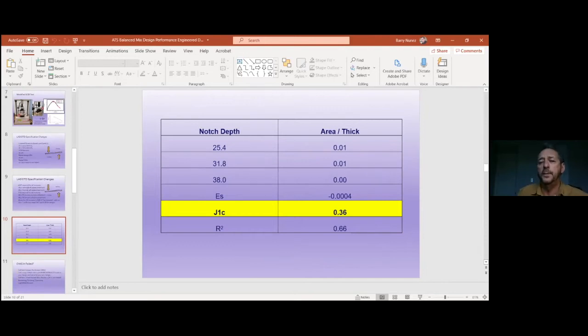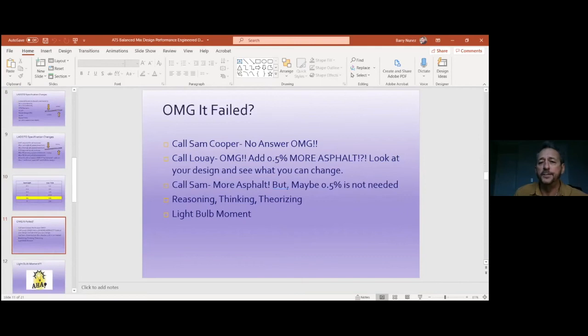The results minimum for a level 1 was a 0.45. Well, 0.5 technically. So you need a 4.5 or above to make that 0.5. And my first one failed. It was a 0.36. So, you know, you're standing there in the lab. I had a technician, Junius Howard, working with me. And we looked at this and we're like, oh goodness, oh my goodness, what do we do?